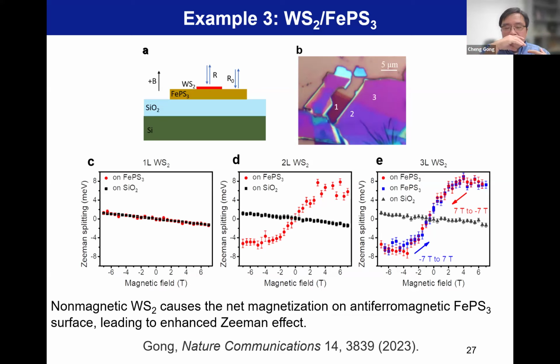So when tungsten sulfide has a K and K-prime valley and you have a four Bohr magneton difference, you should see a 0.2 milli-eV per tesla magnetic field dependent Zeeman splitting. And indeed, when we put one layer tungsten sulfide on silicon oxide or on iron phosphor sulfide, it's a linear curve of about 0.2 milli-eV per tesla.